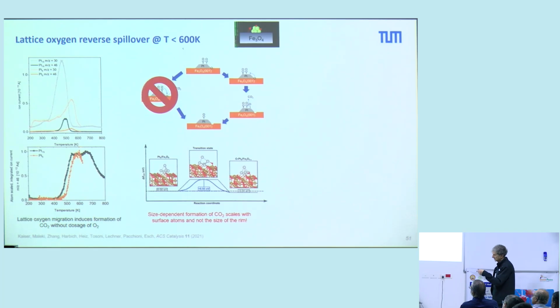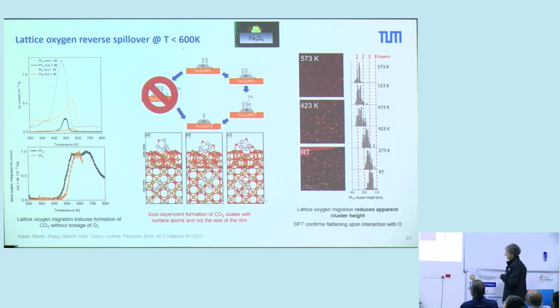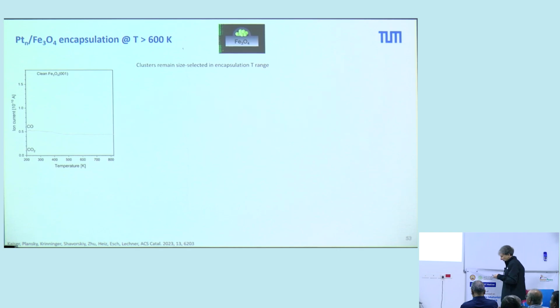This has also been calculated by Gianfranco Pacchioni. The activation energy for this migration is about 1 electron volt. This is also confirmed by these height measurements. You see here for platinum-19 at room temperature the original data. And then you see if we heat up, the distribution remains constant. That means we have the same clusters, but the height is decreased. And also calculations by Gianfranco Pacchioni showed that if you put oxygen on these clusters, they are flattening. Of course, you also have another electronic structure, so you have another STM image. And so this flattening is also another indication that we have this reverse spillover in this temperature range.